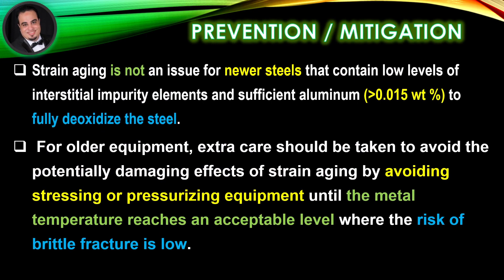Strain aging is not an issue for newer steels that contain low levels of interstitial impurity elements and sufficient aluminum — greater than 0.015 weight percent — to fully deoxidize the steel.